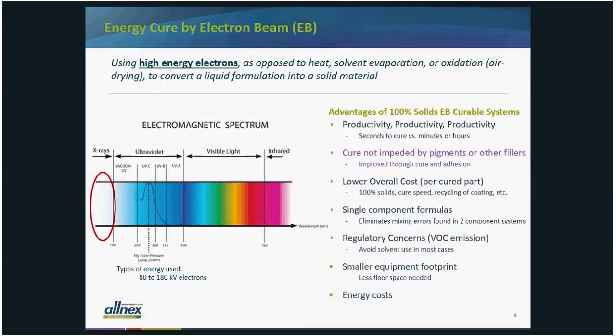So if we look at energy cure by electron beam, we're using high energy electrons, and the energy is much higher with these electrons than the energy of the photons in UV curing. The advantages are mostly the same. It's a very fast cure process, so productivity is high. A lot of the same benefits as with UV curing, but there's an important distinction in that the cure is not impeded by pigments or other fillers. With UV, it's sometimes difficult to cure highly filled systems. Not so with electron beam. You can cure pigmented coatings or inks, or cure filled systems and get good through cure and adhesion easily with electron beam, where you'd have a challenge with UV.